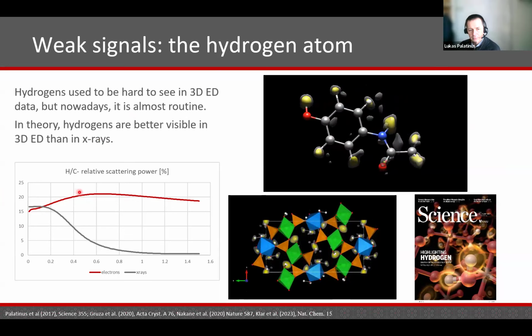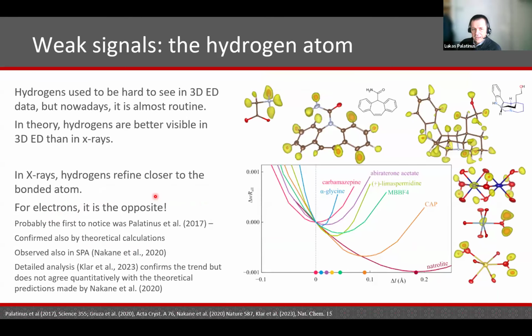So this is the relative scattering power of hydrogen compared to carbon. This is in percent. So at low angles, but there are very, very few reflections at low angles, so this doesn't really count so much. At low angles, the scattering power is similar, but while the scattering power of hydrogen goes down with the scattering angle very dramatically for X-rays, for electrons it remains essentially constant. And therefore, hydrogens are in principle better visible in 3D-ED than in X-rays. Despite that, it's been for a long time considered difficult, but nowadays it's almost routine.